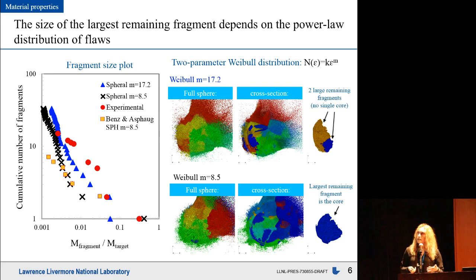In 1991, when this gas gun experiment was being conducted, Nakamura and Fujiwara did not actually measure the K and M parameters for the Yakuno basalt used as the target material. So other groups with SPH codes that wanted to use this gas gun experiment to validate their own codes were subjected to doing arbitrary K and M parameter scans to find simulation results that best match the experimental results.